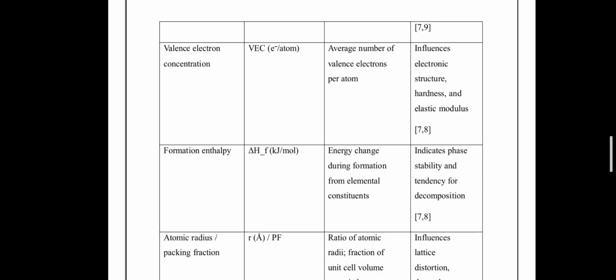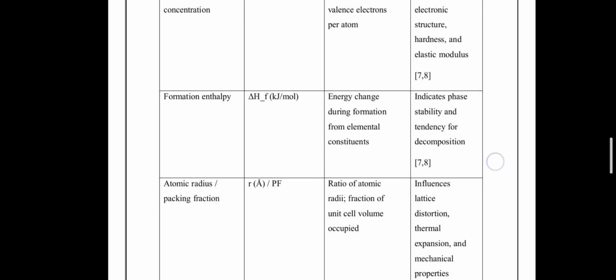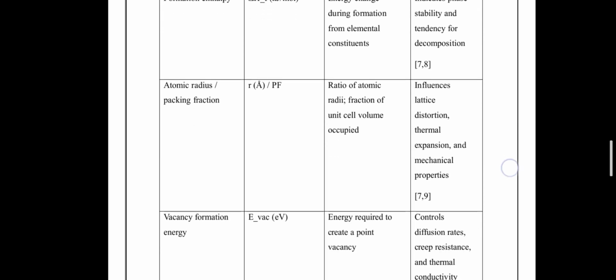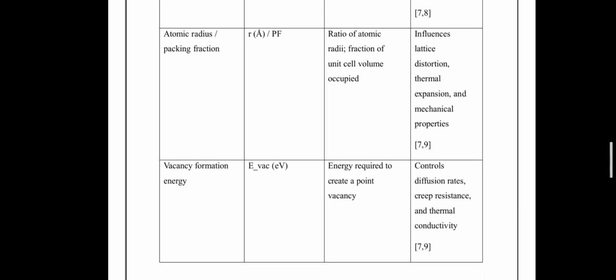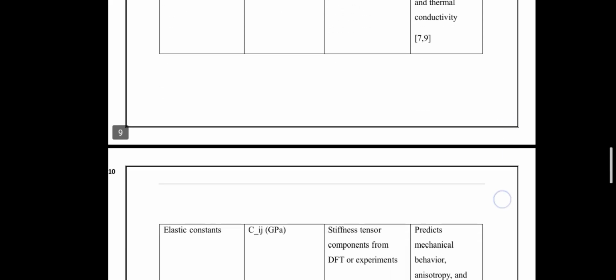Other is the formation enthalpy, that is the energy change during the formation from the elemental constituents. It indicates the phase stability and the tendency for decomposition. Atomic radius, that is the ratio of atomic radii and fraction of unit cell volume occupied, influences the lattice distortion, thermal expansion, and mechanical properties. Other is the vacancy formation energy. It is the energy required to create a point vacancy. It controls the diffusion rate, creep resistance, and thermal conductivity.